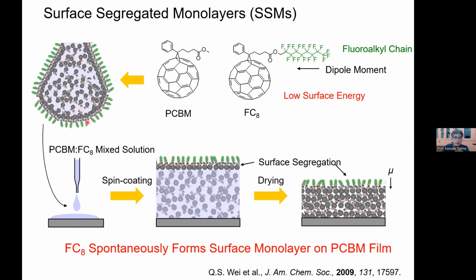Then when you spin coat this solution on top of the substrate, this surface segregated layer remains on the surface of the liquid film. And even after drying, these molecules form a monolayer on top of the solid film with the fluoroalkyl chain sticking out to the air, because this is all about the minimization of the total energy. The surface energy is minimum with the fluoroalkyl chain pointing toward the air.